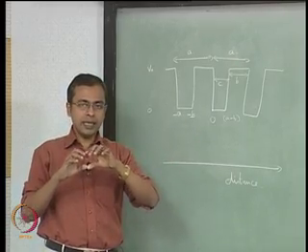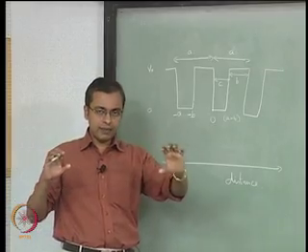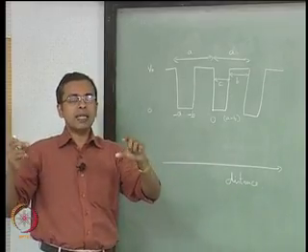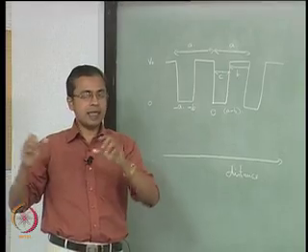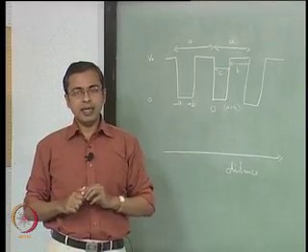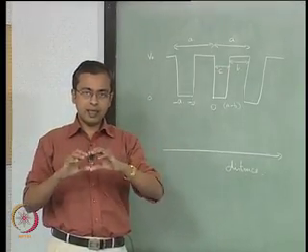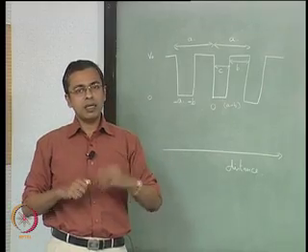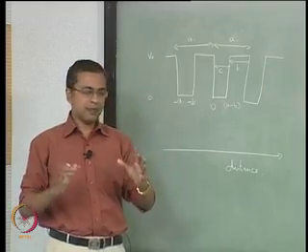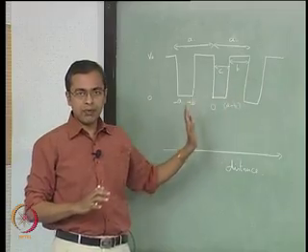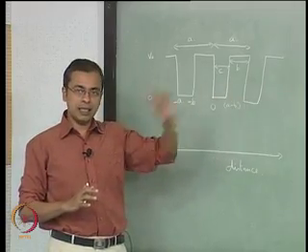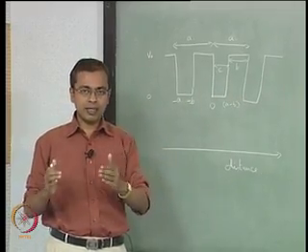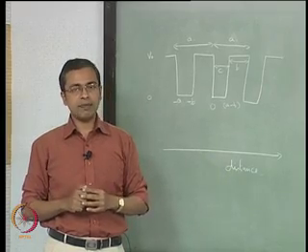The range of values over which the equation is meaningful will represent the allowed energy band, and the range of values where the equation is no longer meaningful will become the band gap. That is how this set of constraints gives us when we are going to have an allowed energy level and when we are going to have a band gap.